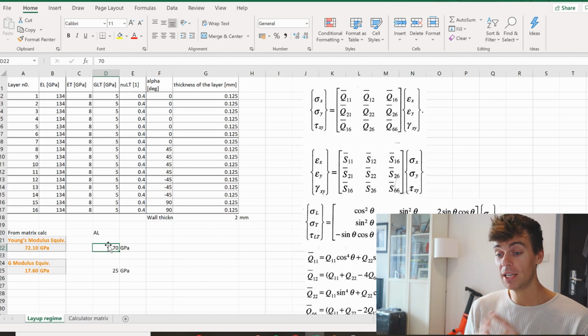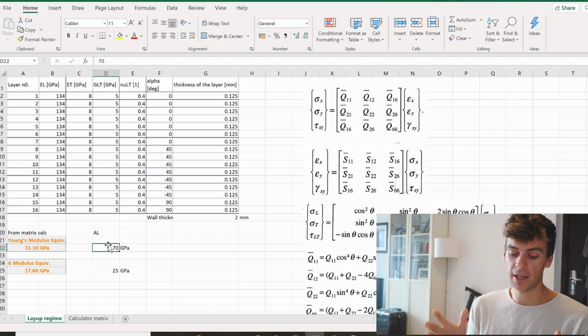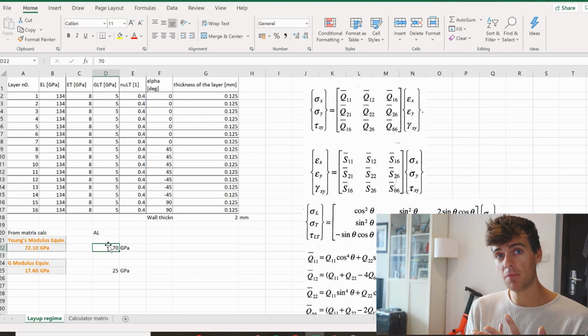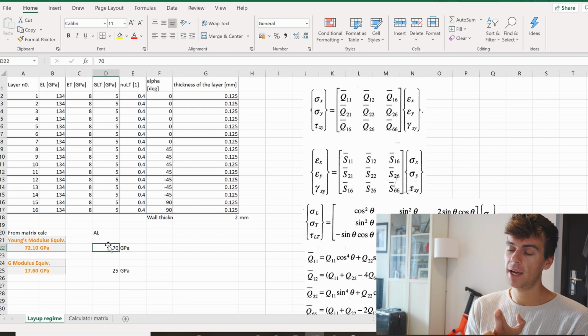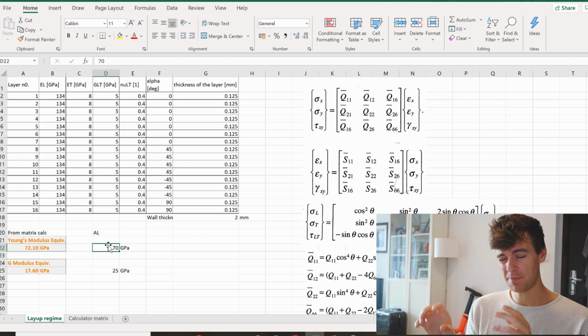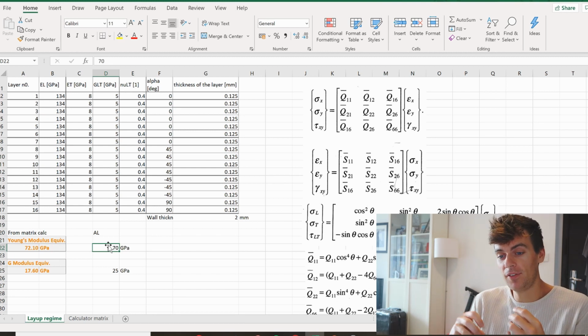So it's not this wonder material, and that's why you do see aluminium bikes out there approaching the same weight, like CAAD12, CAAD13. They're not actually that much heavier than the carbon equivalent. Now in those scenarios I would say they're definitely not going to be as stiff. But let's say you had an aluminium bike that was 1500 grams and the carbon one was 1000 grams, then you could probably say it's around the same stiffness. So you're not losing out massively if you're buying a heavier aluminium bike. You're probably not going to have a less stiff bike than a carbon bike.